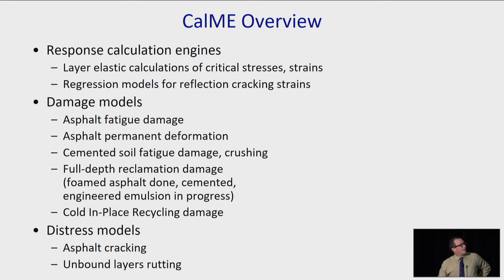The response, we're using layer elastic. We're using regression models for the reflective cracking strains. We use the same approach for fatigue of reflective cracking as we use for bottom-up fatigue cracking, except we predict the tensile strains using regression equations, which are run through thousands of finite element runs. The damage models are shown here.